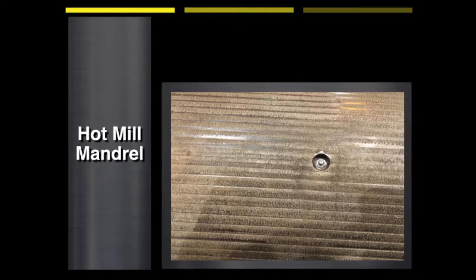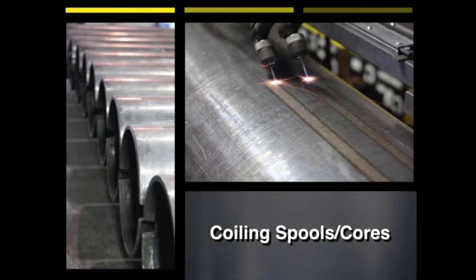The next advancement was needed in order to reduce the coiling cycle time on a belt wrapper style cold mill. To do that, we added textured carbide coating to the face of the coiling spools using ESD. The textured coating applied to the spools allowed the mill operator to pull tension sooner and get up to operating speed much faster than before.